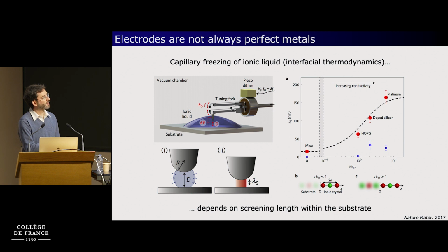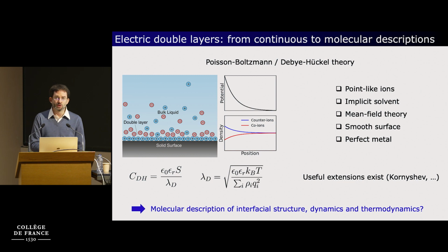This capillary freezing distance can be rationalized in terms of the screening of the electrostatic potential and the charge distribution inside the metal via the so-called Thomas-Fermi screening length, which is the inverse of this k_TF parameter here. I'll get back to that point later on, but the idea is that the electronic structure of the metal has an influence on the interfacial thermodynamics. So from the modeling point of view, the standard description of charged solid-liquid interfaces is that of an electric double layer. So you have a layer of charges inside the solid and a layer of charge in the liquid that compensates that of the solid.